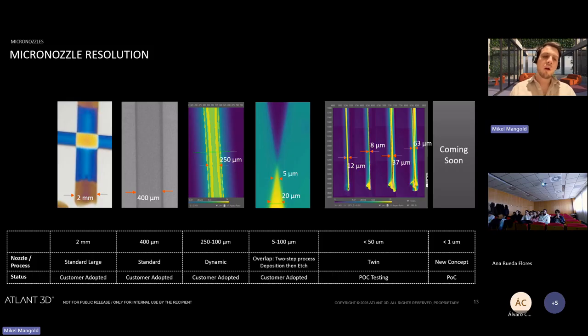But we can do super well at the moment at 250 microns, 400 microns, which is applicable to a number of applications like sensors, protective layers on certain materials, and MEMS. We now have optical application requests for defense and beyond, where we developed a nozzle for 2 millimeter passes, and then we can coat, for instance, a certain area to have a certain refractive index, or we can go lower, as you can see, up to 8 micrometers. That was basically a deposition and an etching step of the line to get such small lines. So that's what we did.